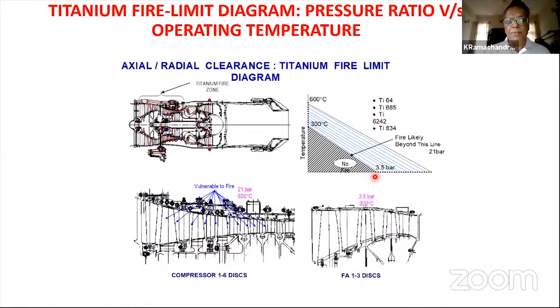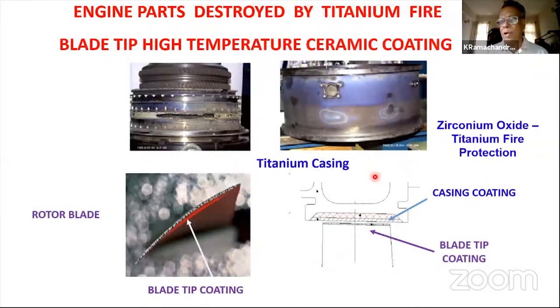And so if there is a problem with the growth of the blades, a malfunctioning of the spool, there could be a blade to casing rub, which will result in titanium being released, and this gets ionized, and there is an imminent explosive fire, and you must lose the whole engine and perhaps the aircraft. So we need to be looking at preventing titanium rub by having a blade tip coating. It looks very silly, but the tip of that blade is so thin, you must be able to coat the zirconia on this, and also coating on the inside of the casing. So the titanium is prevented from rubbing against each other, and we prevent the possibility of titanium fire.